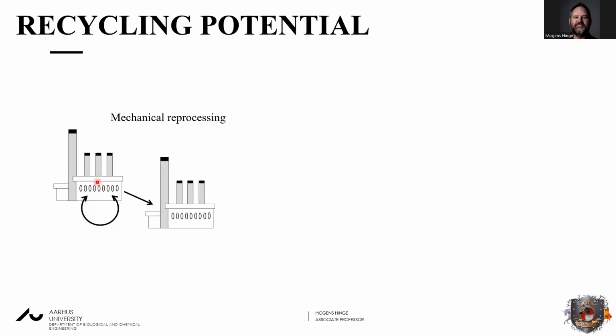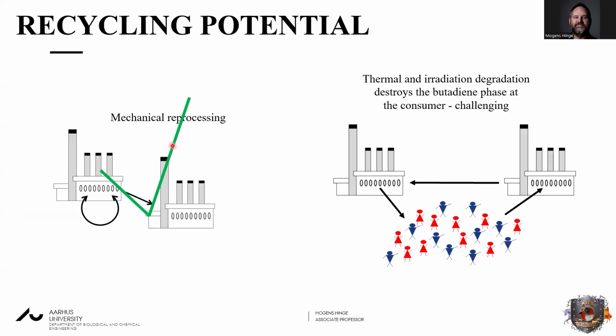But we could also imagine the situation where the scrap cannot be reused internally in the same factory, but can be shipped to another factory that can use it. And again, same story, it does seem like we can easily do this. So at least with 10 cycles, we don't see a lot of degradation of properties. Now, the second thing is if you have a factory manufacturing a product and sending it out to consumers, you, me, and everybody, then we use it for a while and we expose it to heat and UV and all of these things for a longer time than when you reprocess it in your facility. So that basically means that here you will have a lot of degradation.